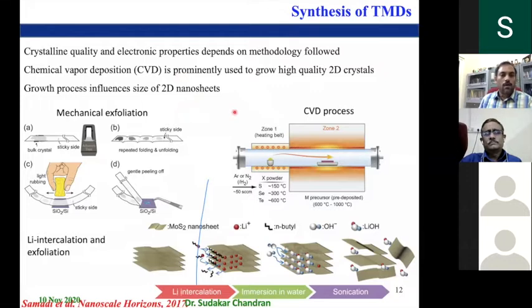To comment on how these transition metal dichalcogenide layers, nanosheets are prepared, one of the simple methods is mechanical exfoliation. You can get the crystalline quality for electrical property studies. What you need to do is take an adhesive tape, put it onto the bulk crystal and strip it off. A couple of layers will stick onto it, and you can repeat this process in such a way that finally you will have a single layer sticking onto the tape, and that you can carefully transfer onto the silicon dioxide substrate. And finally you have these monolayer crystals, and then you can put the probes and study.